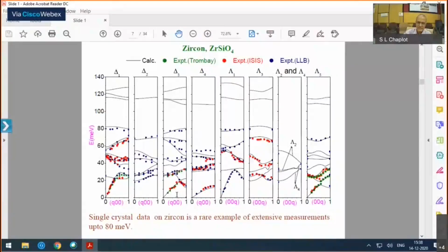Another kind of situation is that there may be certain phonons which contribute very strongly to phenomena like thermal conductivity, being highly anharmonic, so one is interested in measuring those phonons and their lifetimes and dispersion around it, which are key components in estimating the thermal conductivity contributions.